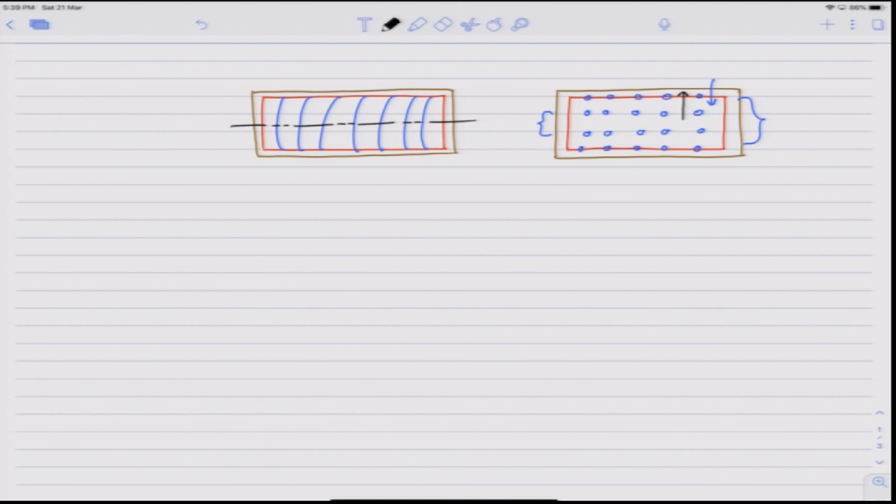And this was a classic experiment because it helped in establishing diffusion mechanism based on vacancies, which was not popular at that time. Earlier, the popular mechanisms were the direct exchange mechanisms or ring mechanisms, but this helped giving a strong foundation for the vacancy mechanism of diffusion.